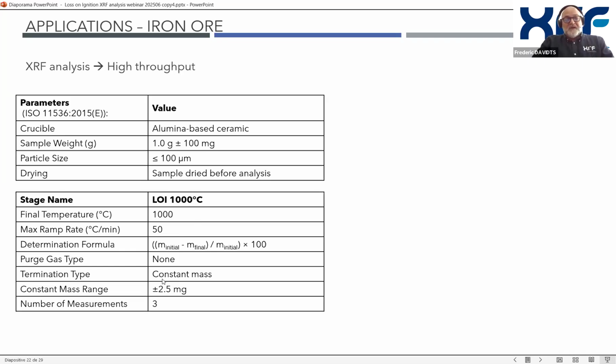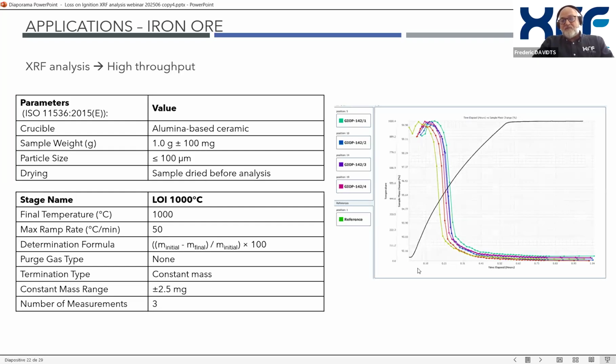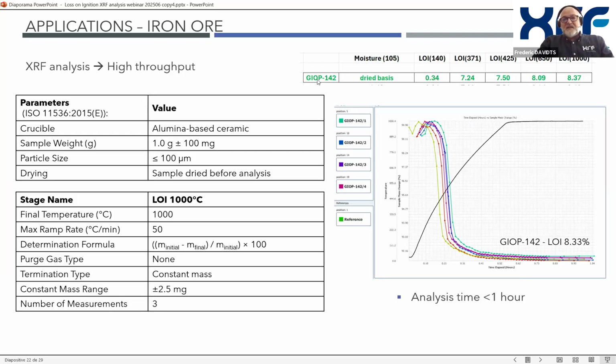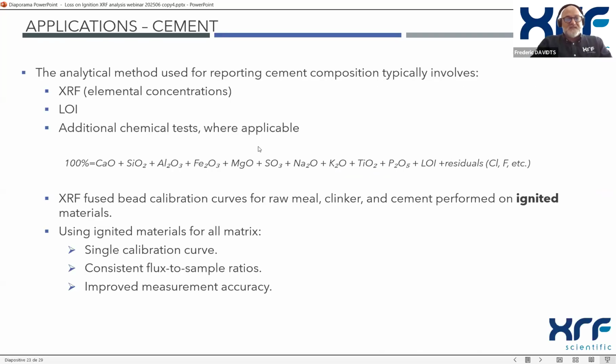And again, to determine the mass constancy, we will do repeated weighing with a mass range of plus minus 2.5 milligram. And we can see on this thermograph that we have a fast heating ramp, and we reach the mass constancy after less than an hour. So it's really good and very fast. And again, the sample used was the reference GIOP-142, and we can see by the results that even by going directly to the last step, we retrieve the same loss of ignition. So the bias is really good.